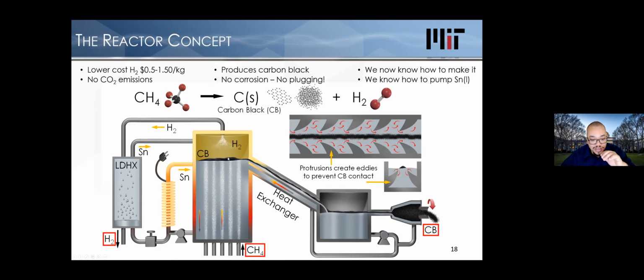Now that you've got this carbon floating on the tin, there's about a factor of 2 or so density difference between carbon and tin. It's about 2.5. So the carbon will not sink into the tin and it'll float. And because we can pump the liquid tin, we can now use that as a mechanism to get the carbon out in a continuous manner. So we can flow the tin and carry out the carbon with it floating on the surface.